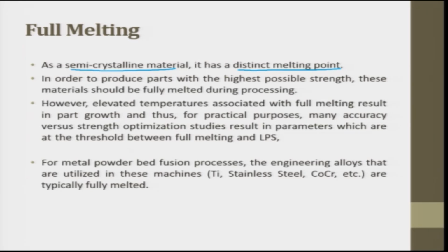However, elevated temperature associated with full melting results in part growth, and thus for practical purposes many accuracy versus strength optimization studies result in parameters which are at the threshold between full melting and LPS. So, this portion is very important.